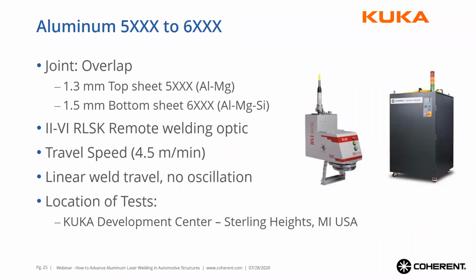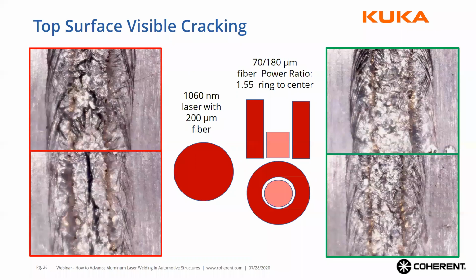What they observed is that the left side here is what you typically see with a standard fiber laser sold on the market. You'll have either a top hat or Gaussian mode fiber laser on the left side. Out of a 200 micron fiber, you see there's a lot of micro cracking visible on the surface. On the right side is the ring fiber laser with an optimized ring to center ratio. Here they used a ring to center power ratio of 1.55, which turned out to be their magical ratio for this specific configuration, and you see no cracking.